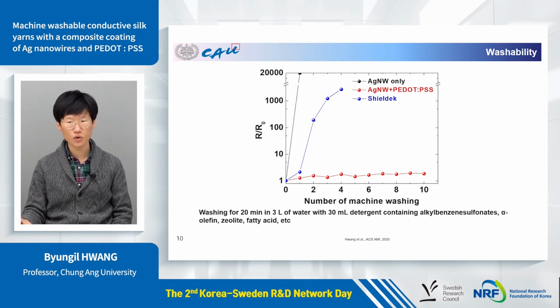From this result, we could confirm that the machine washability, which resulted from the attraction between the PSS and silk yarns, was kept even after inserting silver nanowires between the PSS and silk yarn surface.